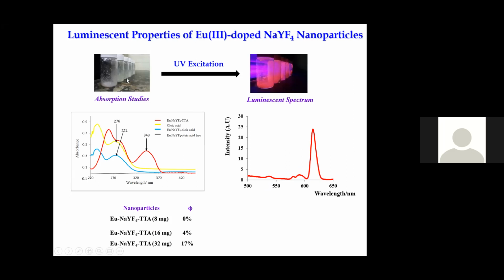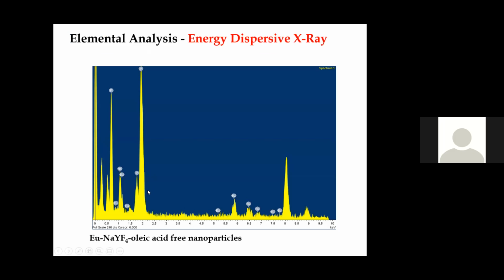So again, we coat the surface of the nanoparticles with our ligand. You see the nanoparticles are white in color. They don't absorb visible light. They absorb UV, and when you shine light, you see they emit red light. This is the emission spectrum. It shows the emission at 615 nanometers. The absorption spectrum shows it absorbs UV light. When you coat the nanoparticles with the ligand, they get the characteristic features of the ligand. We can fine tune the surface coating ligand amount, and we can enhance the quantum yield. Now we are at 17%, which is a big deal for us, going from 4% to 17%, showing for the first time in the world that you can do this process and excite the nanoparticle by using a surface coating ligand. So I think I've told you the full story here, but I'm going to show you some more examples.